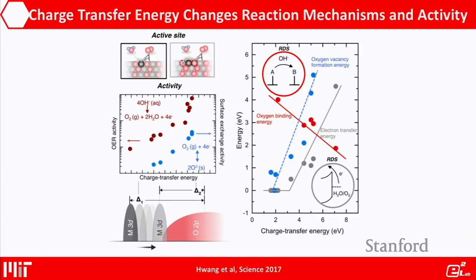If you make the metal oxide more covalent, pushing the metal d states into the p states, you can increase the catalytic activity by 2 orders of magnitude in, let's say, basic solution. In more ionic metal oxides, only the metal serves as active sites that adsorb and do the deprotonation reactions. But as we make the compound more covalent, the oxygen also becomes an active site. The oxygen on the surface and the metal are equally active towards splitting of water to evolve oxygen.